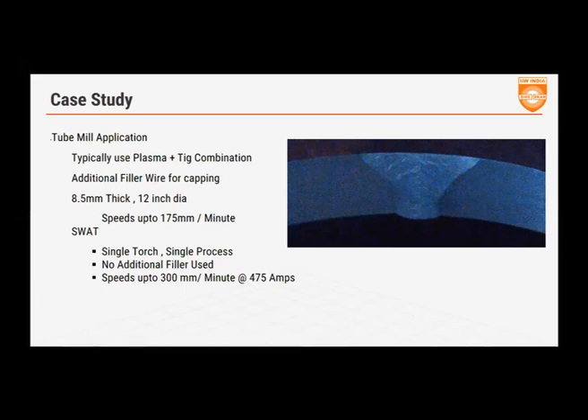When we use SWAT, we were able to use a single TIG torch, single process, no additional filler wire, and we got speeds up to 300 millimeters per minute on an 8.5 mm thick tube. This is that pipe here.